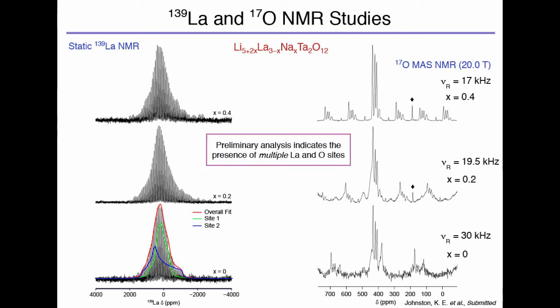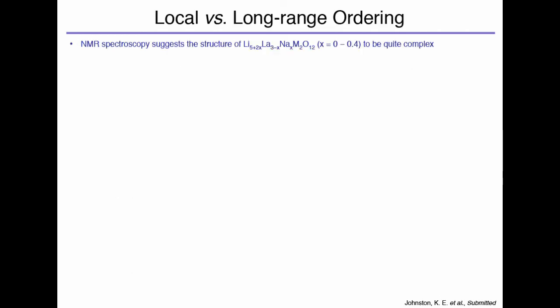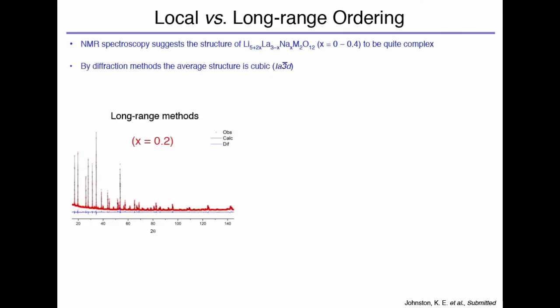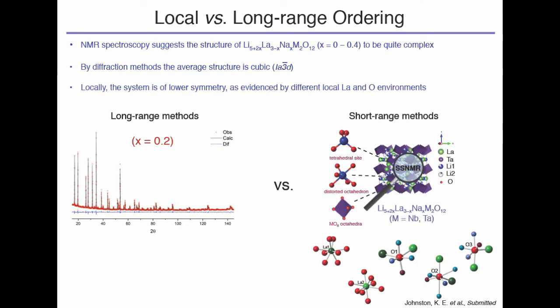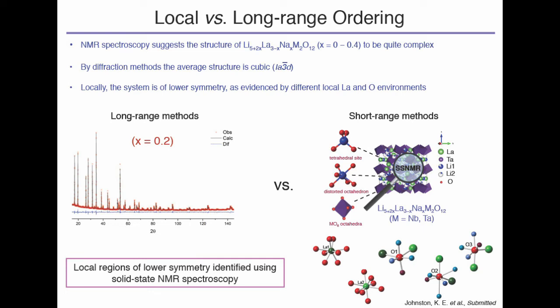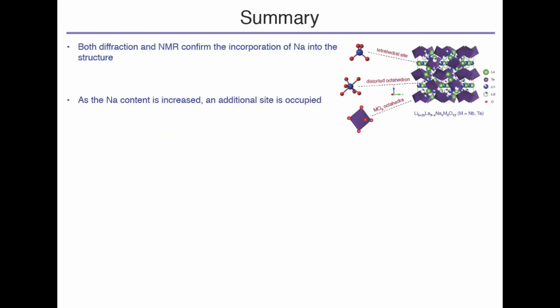And I guess the interesting point here is that NMR is telling us something completely different to the diffraction: that there are multiple lanthanum sites and multiple oxygen sites, which is different to the diffraction, where there's one of each. So NMR is really suggesting that we have a really quite complicated structure here for these lithium-stuffed garnets. By diffraction methods, it looks like it's on average cubic, but if you start to look short range using techniques such as NMR, you actually find that the symmetry is much lower. That's things like the different number of lanthanum and oxygen sites. So you're actually getting a lot more structural information from these local probes.